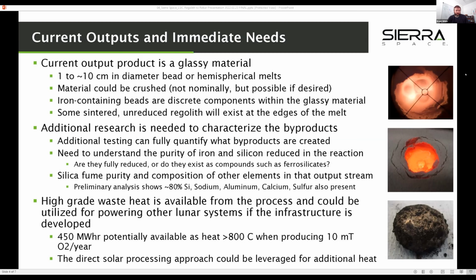The silica fume, we've done testing on that. So by mass, that is about 80% silicon. The sodium is around 6%, and then aluminum, calcium, sulfur, and so on are all down in the 1 or 2% range. But that's obviously going to be dependent on your feedstock as well.